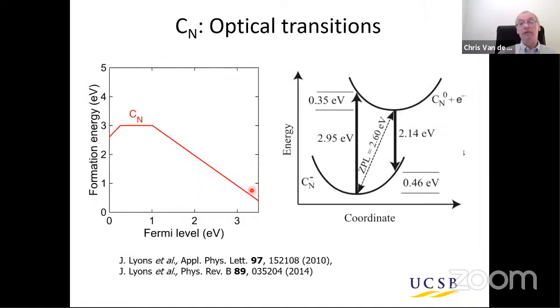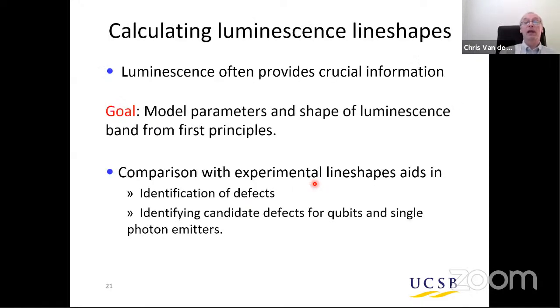So we can now model all of these things with first principles calculations based on density functional theory. This is a formation energy diagram again, in which you can recognize this neutral charge state, negative charge state. Here's the configuration coordinate diagram, but now based on actual calculated numbers. And to make a long story short, here you see that we expect the emission to occur preferentially at an energy of 2.14 eV, which is basically smack at the center of that yellow luminescence. Okay, so this is basically conclusive proof that simply a substitutional carbon atom in gallium nitride gives you that yellow luminescence. The microscopic origin was elusive for a very long time. Okay. So far I focused on what the most likely optical transition process is by looking at these vertical transitions.